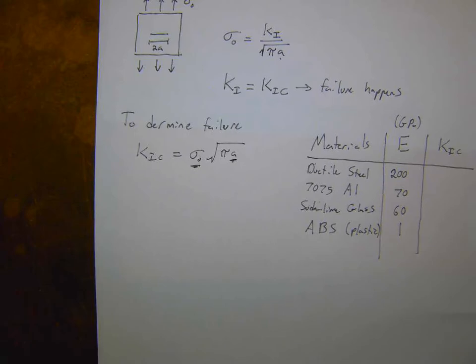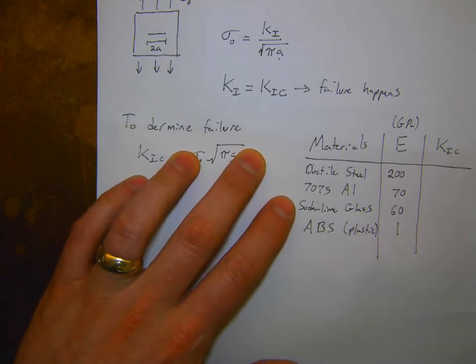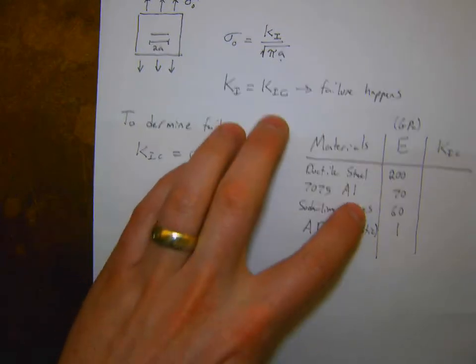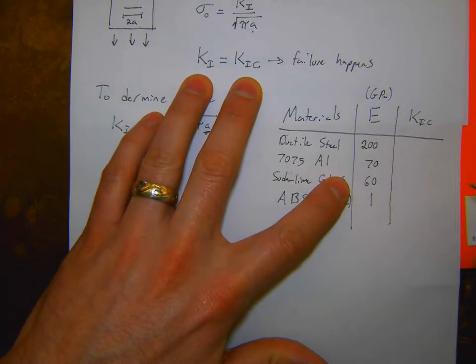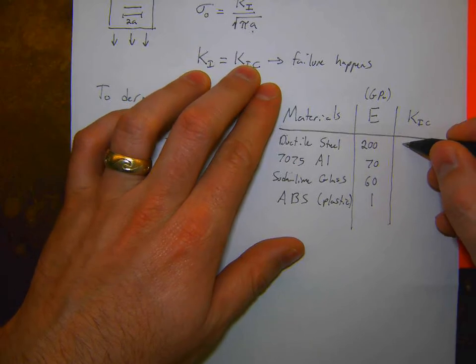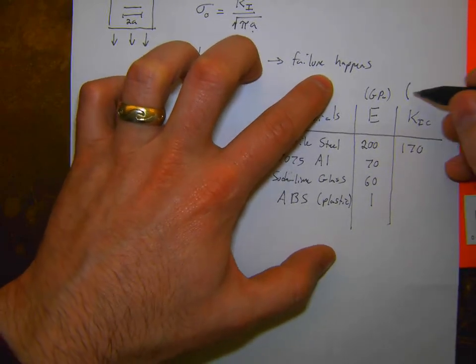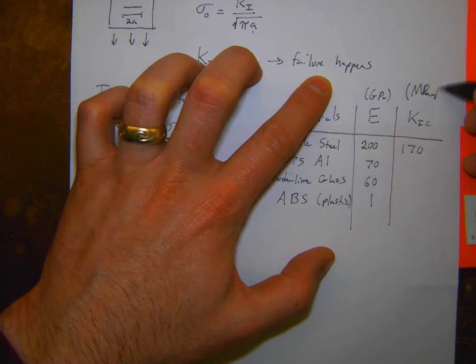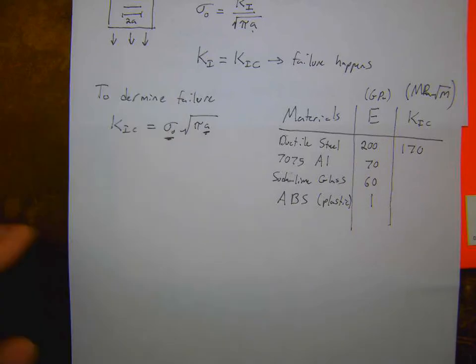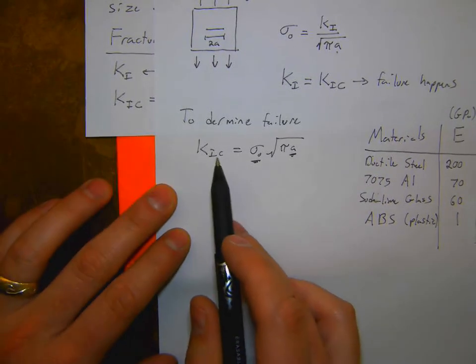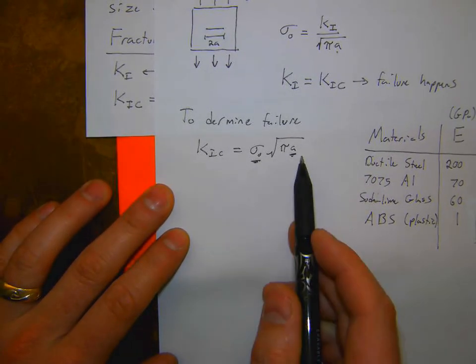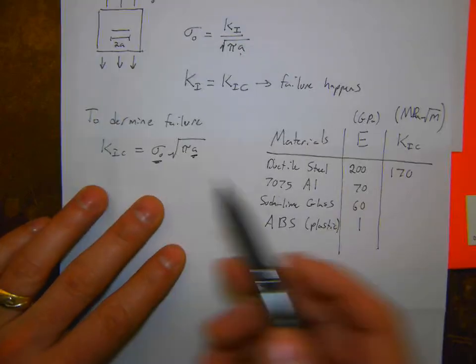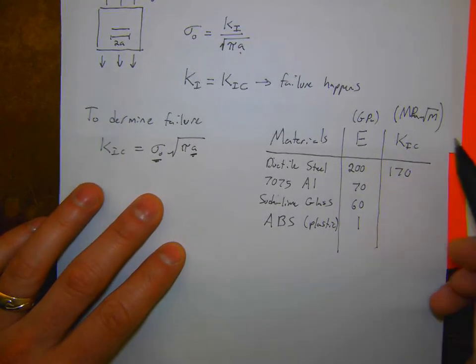Okay. So for these particular materials, I'm going to show you a big Ashby plot of all these in a second. For ductile steels, generally, yeah, this would have the highest fracture toughness, something like 170. And the units for this are weird. They're megapascal square root meters. So because that K_IC is a yield strength and then there's a length dependence in there, the units end up having a meter in there.